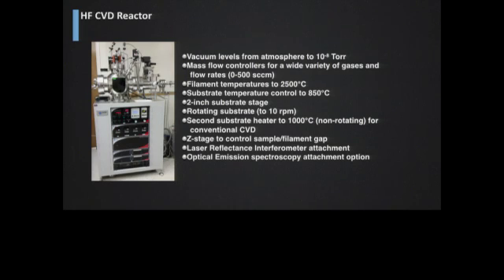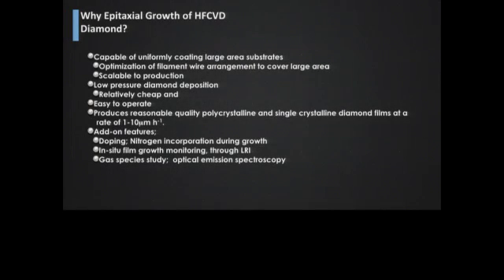And then recently we've started out with some optical emission spectroscopy, and we can bias the substrate relative to the filaments, and we can actually create a plasma as well as the hot filament effect, and we call that plasma enhanced nucleation, and that can speed up the growth rate as high as 10 microns an hour. Typically, without the biasing, we're about a quarter to a half of a micron an hour, somewhere in that neighborhood, depending on the gas flow. So it's capable of uniform growth.